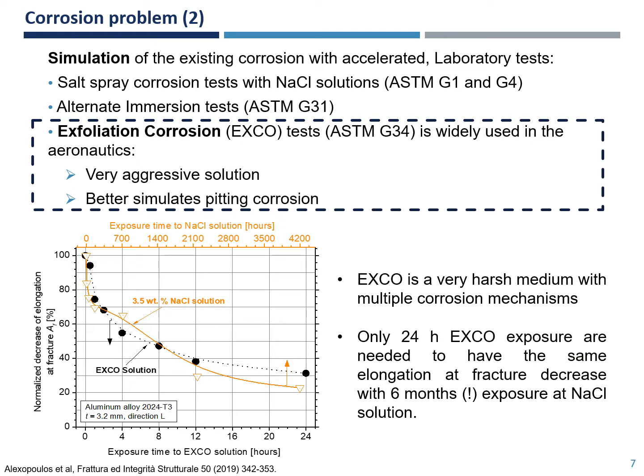Among the different accelerated laboratory corrosion tests, the exfoliation corrosion test was used in the present work since it is a very aggressive solution and it reduces the time needed for the experimental procedure. According to previous work of the authors, only 24 hours of exposure are needed to have the same elongation fracture degradation as 6 months of exposure to a NaCl solution.